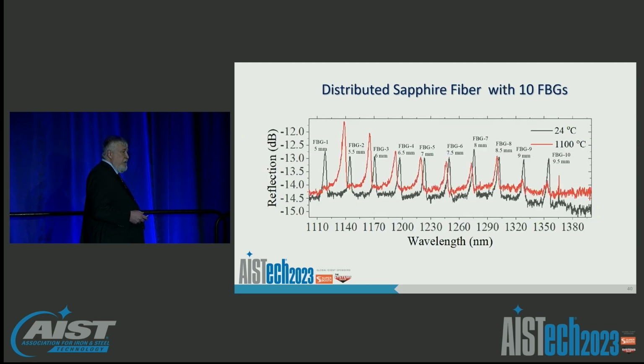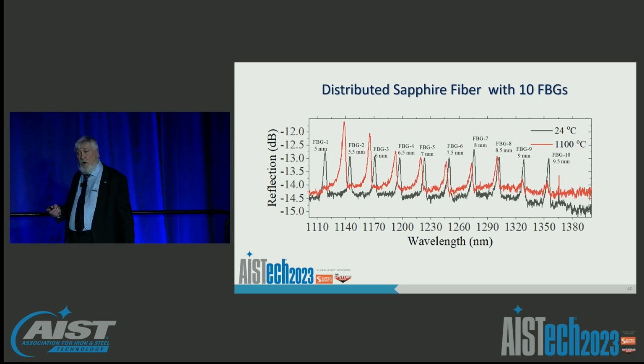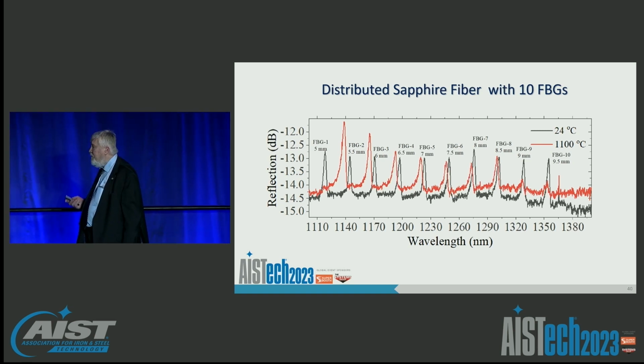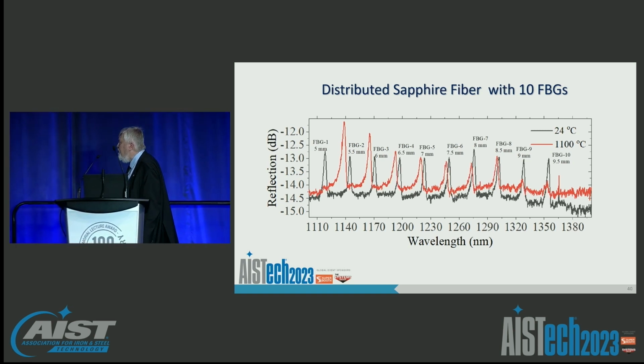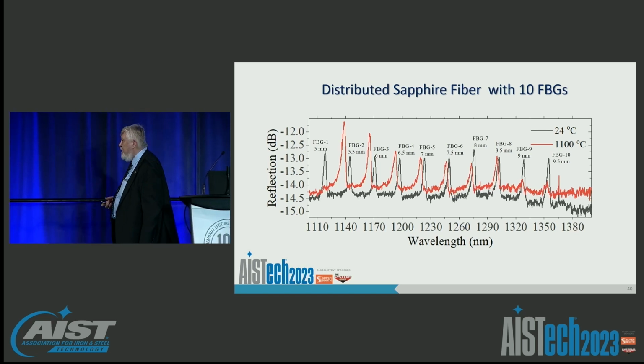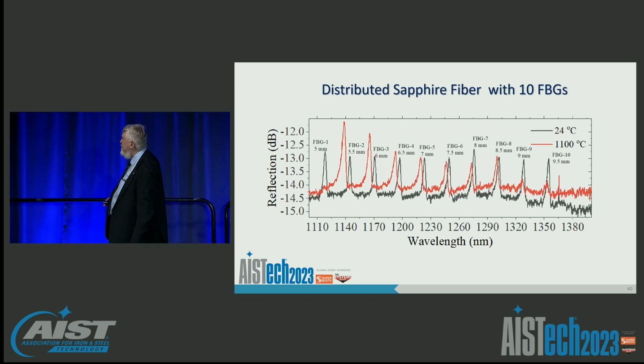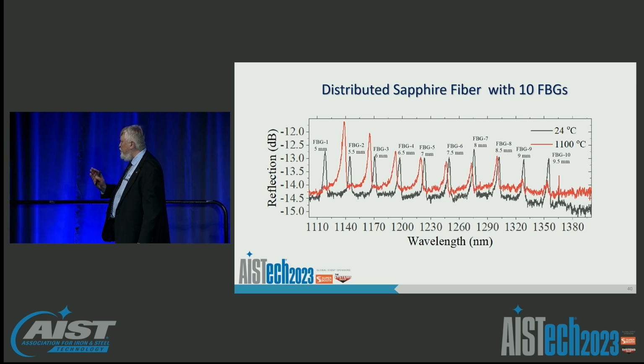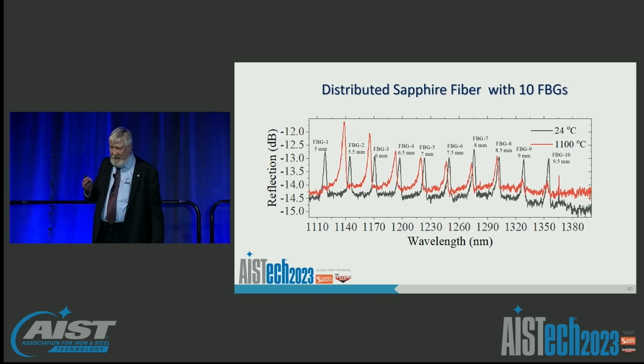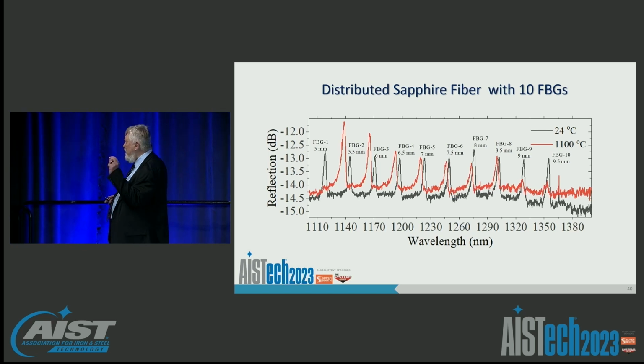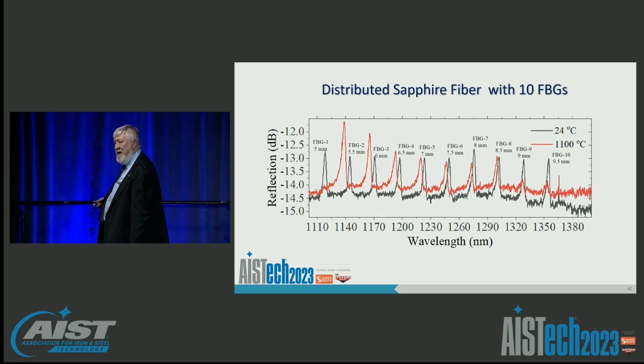Distributed temperature measurement is an important one, and we've actually also been able to demonstrate now that these fibers can look at a larger number of sensors than 3. In fact, we've now demonstrated up to 10 FBGs in a fiber that is a sapphire fiber system. And then each base frequency will shift as a function of temperature, and each can be tracked to have an individual measurement point along that length of that fiber.